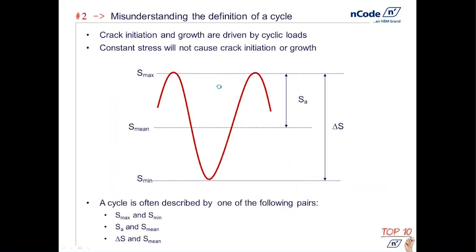The second common mistake is one that is about the definition of a cycle, and it is often misunderstood. A crack, whether we're going to be initiating a crack or growing a crack, is going to be driven by cyclic loads. These cyclic loads in turn are going to create cyclic stresses or strains on a structure. Hot spots where we have sharp geometric features are going to appear and that's usually where we're going to see the damage occurring.